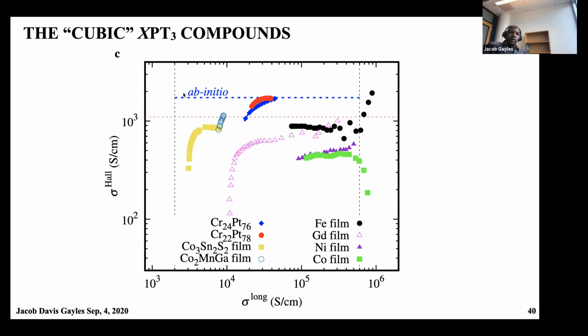And so focusing on this, we also see some interesting features here. One is these chromium platinum materials have a very excellent agreement with the theoretical values as compared to the cobalt-3 tin sulfide, which also does not match up for the films to the theoretical value, where the single crystals do. And this is actually something quite common for these topological materials, that they are not matched very well with the theoretical values for the films. And this may just be due to sample preparation and impurities in the system. However, with this chromium platinum, as I showed before, we do have these impurities in there, and you get a very robust anomalous Hall effect from this.